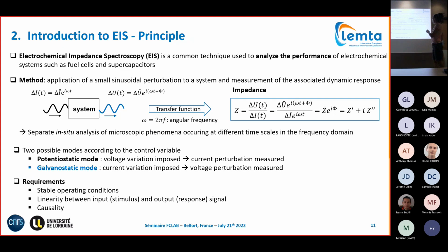In order to perform EIS, you have some requirements to respect. First, you need stable operating conditions for sure. You have to be sure that you have a linearity between the control signal and your response signal. And then, you have to show that there's some causality between the response measured and the perturbation you apply.